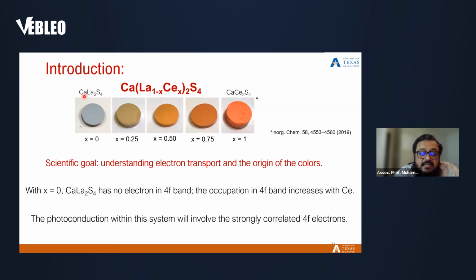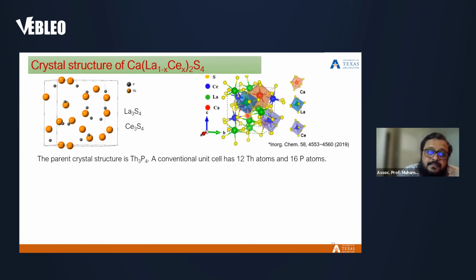With no cerium, calcium lanthanum sulfide, there is no occupied 4f electron compared to this solid solution. Cerium, the last end, x equals 1, calcium cerium sulfide, has the highest density of occupied 4f electrons. And we know that 4f electrons are highly localized electrons. That means a strongly correlated system. The crystal structure of these materials, of this solid solution, the parent structure is thorium phosphide structure. So thorium phosphide structure remains the same whether it becomes lanthanum sulfide or cerium sulfide, or when we start mixing them with varying concentration of cerium. The structure remains the same, and this has been verified by our collaborator at UTA from neutron diffraction measurement. We know that the structure remains the same.